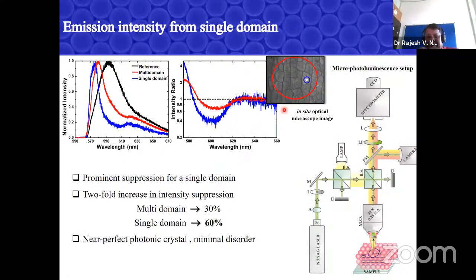Then we were happy with that. We got the nice frequency gap. Can we do emission measurements with the samples? So what we did was make samples with dye-incorporated spheres, where the dye is the emitter. We made a setup again to measure the PL spectra from a small region of the sample, just like the reflectivity. Again, I have a camera so that I know exactly where I'm measuring the sample.